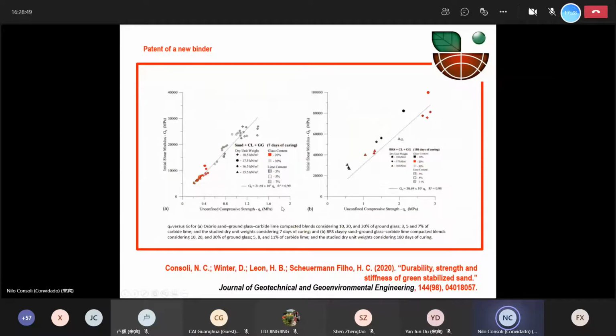In 2020, here we have a paper that was published at the Journal of Geotechnical and Geoenvironmental Engineering from ISEG, and we show this cement cured for 7 or 180 days, and the relation between the initial shear modulus and unconfined compressive strength that we can get. So we mix this cement with sand, and here we have a fine sand. This is a uniform sand. This is a non-uniform sand, with different periods of curing, and they reach some strength.